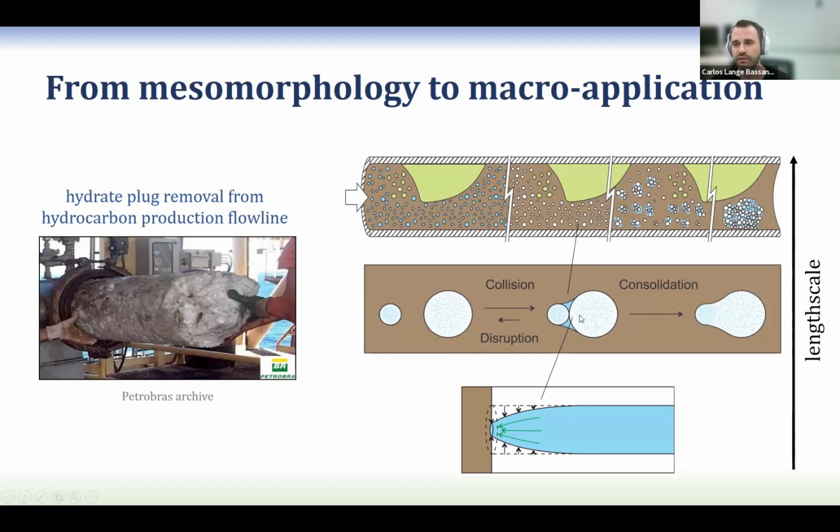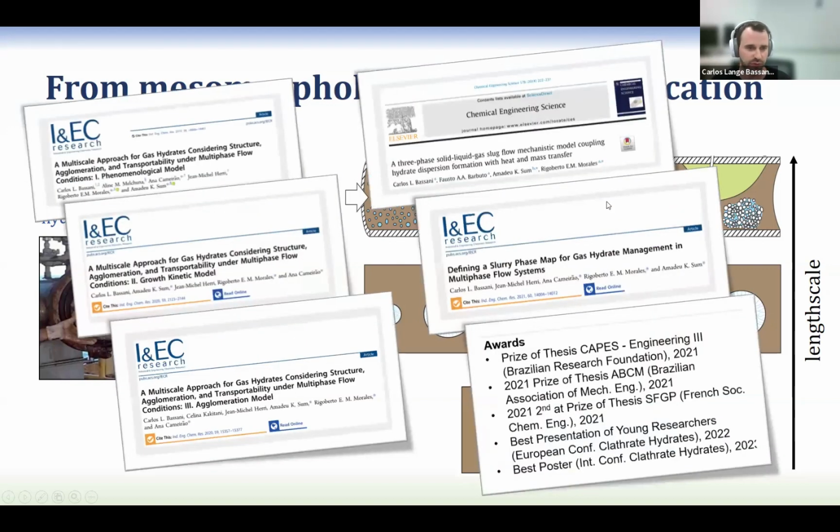And then we ask, when does this liquid bridge happen? And the answer, one scale lower, is in the porous medium. This bridge only happens during the time scale this pore is open and the water can go out. Once the pores close, there is no agglomeration anymore. So all of this coupling between the pore scale, the particle scale, the agglomeration and the flow, you can find in a series of papers here.